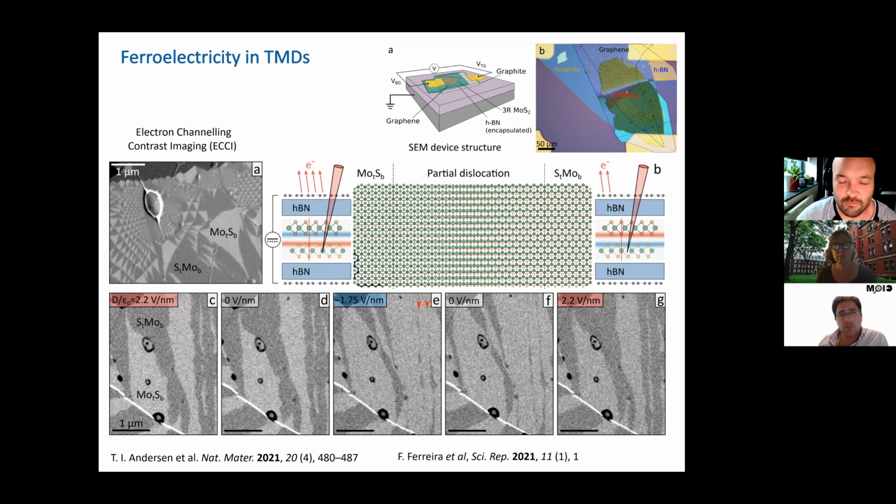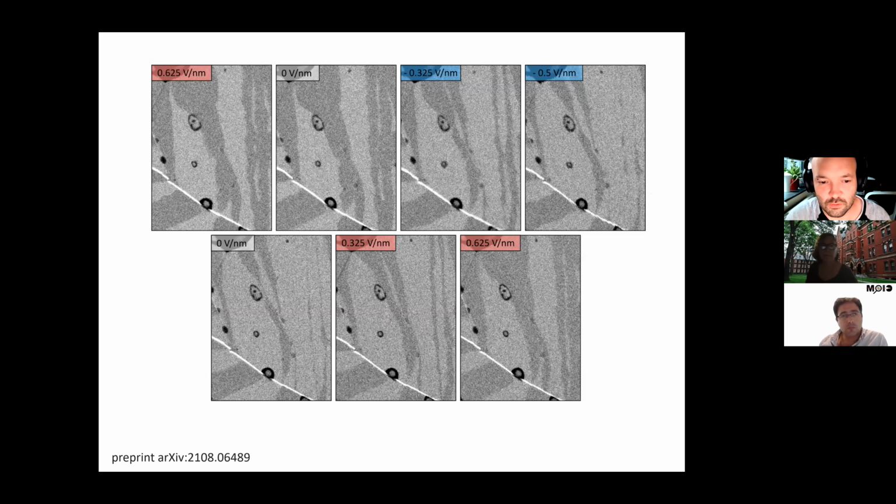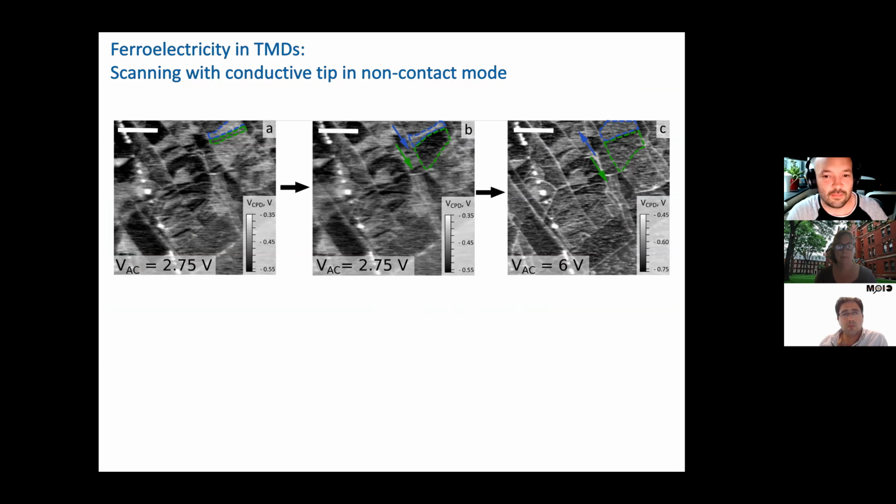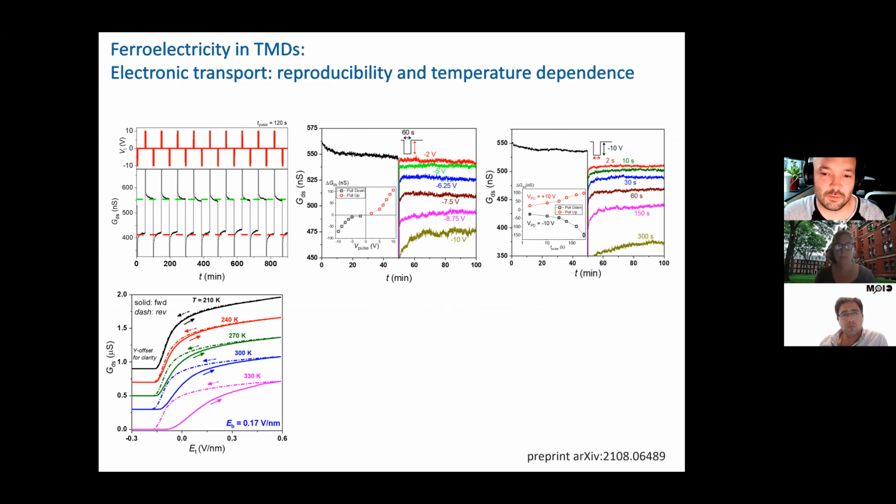So we didn't do any very fast measurements. I would say that the majority of what we can say, because we typically measure DC or low frequency transport, is that on the scale of some seconds, there is a huge change in conductivity. And then over the scale of the next perhaps 10 minutes, you would see a slow relaxation on top of that, which is smaller compared to the initial drop.